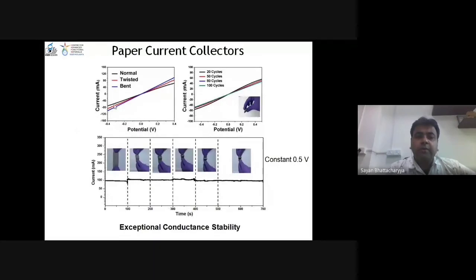So basically, here what happens is, if you, this is a normal one, we twist or bend it, you see the current voltage curves do not change that much. And over many cycles also, they are more or less constant. And over a longer time, stability-wise, if you bend it, this is the plane paper, fold it multiple times as you want, the current doesn't change at a constant voltage. That means that it has exceptional conductance stability.